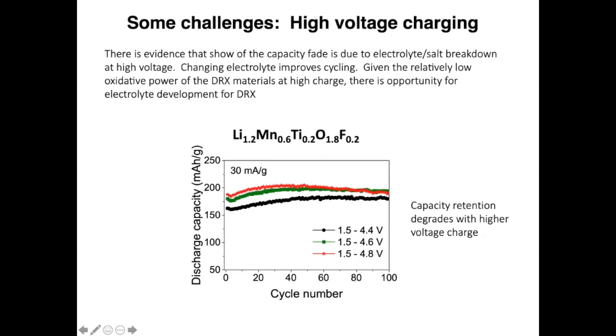We have done work in a larger DRX team with Guoying Chen at LBNL and Robert Kostecki, and there is strong evidence that this is actually a breakdown of the LiPF6 salt on the surface of these materials. We use a classic electrolyte for this today, LiPF6 in carbonate solvents, and it is not clear how much of this is due to the material because there is significant electrolyte breakdown. Also in DEMS, you see CO2 evolution that is clearly arising from solvent breakdown.